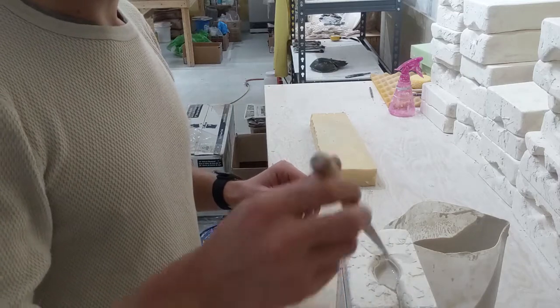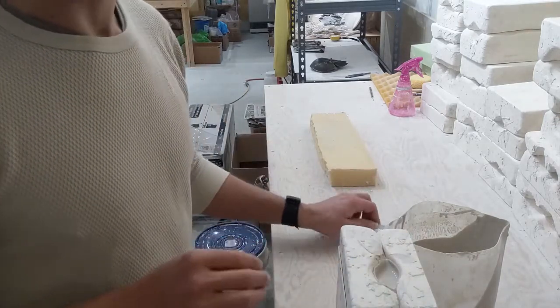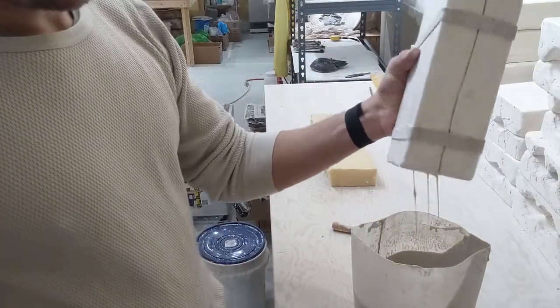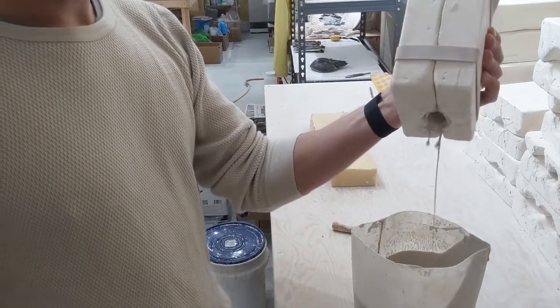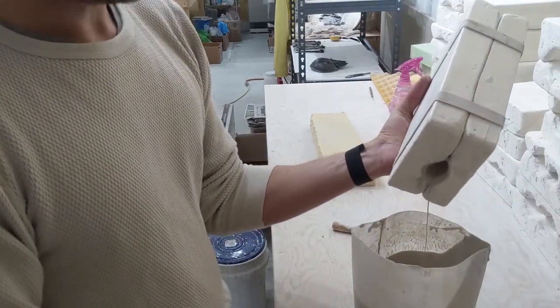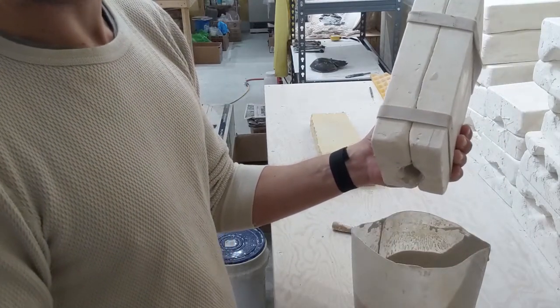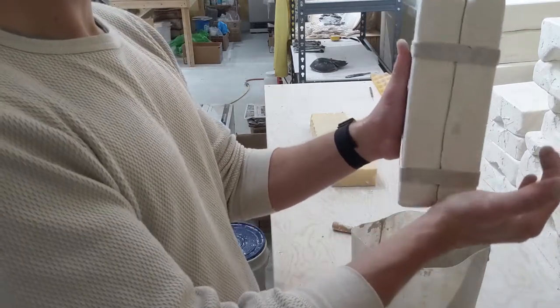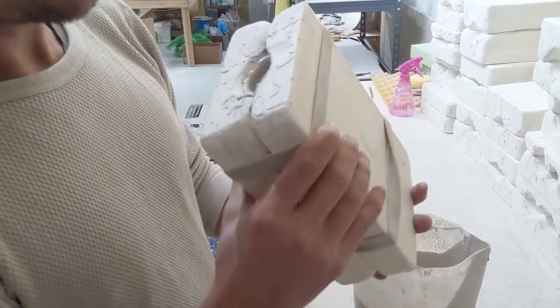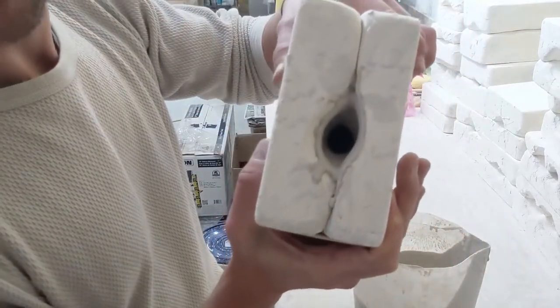What I'm doing now is just using a little pottery knife to kind of stir the slip up in there, being careful not to hit the edges because we don't want to warp the actual object itself. This will just make it pour out a little bit easier. So I'm just going to take this and flip it over the actual slip bucket. You can see all that slip draining out — I'll make sure we get it all. Sometimes you'll get air pockets in there that will prevent some of the slip from leaking out. That's not always a problem, but it will sometimes cause the actual object to be much thicker and heavier than it needs to be. We try to get these as uniform as we can. So you can see now it's hollow inside and you have a pretty thin shell.